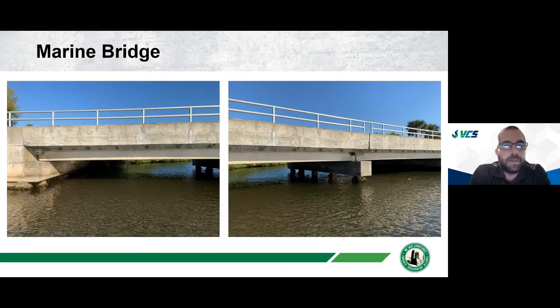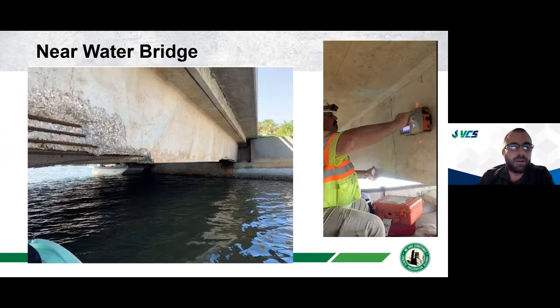This is a marine bridge that was built very close to the water, as you can see, in a Florida environment. And this is actually precast double T's. Precast double T's like this are not really designed to be this close to the water. Very low cover depth to the steel on these elements. And so we were asked to go out with GPR and assess the cover depth and do a durability model for the structure to understand what the remaining service life would be.